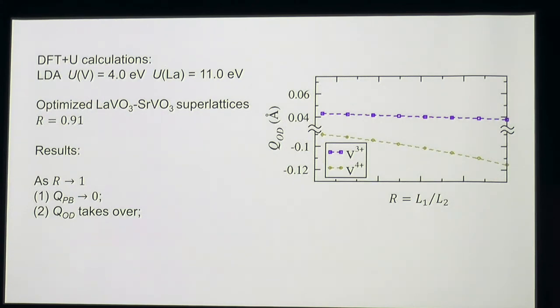In this study, we carry out density functional theory plus U calculations for the superlattice structure, and we found for the optimized structure, the value of R is 0.91. Then we artificially increase R to 1, and for each R value, we optimize the structure with only R fixed.